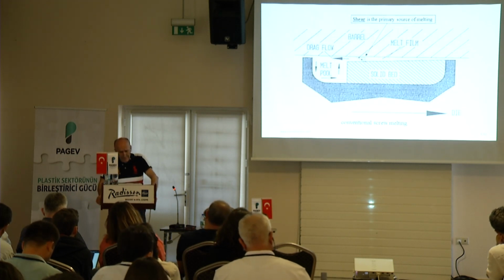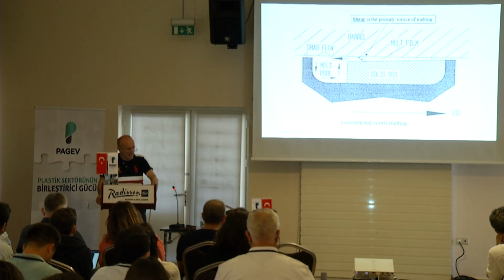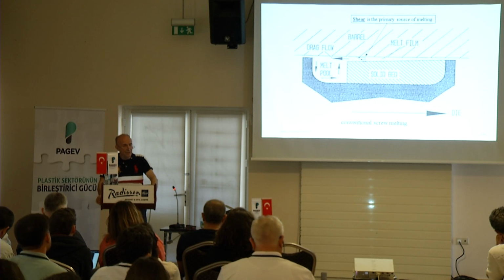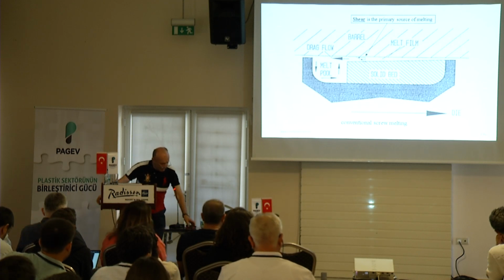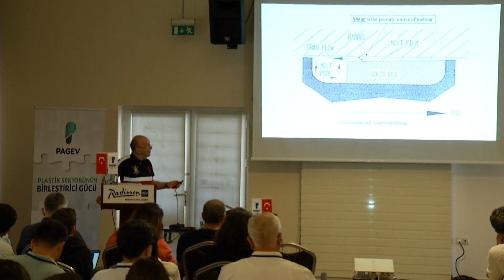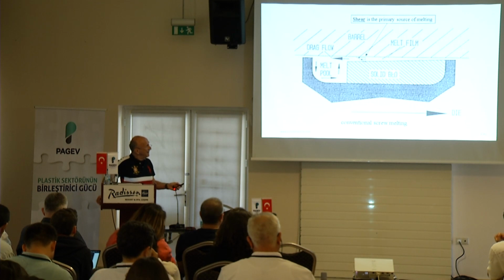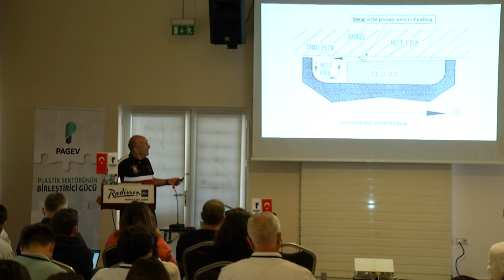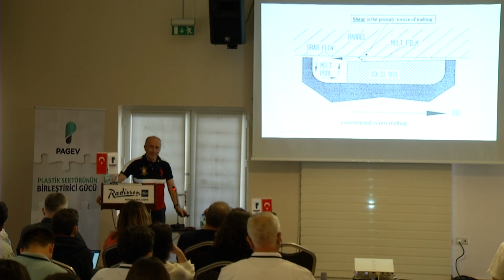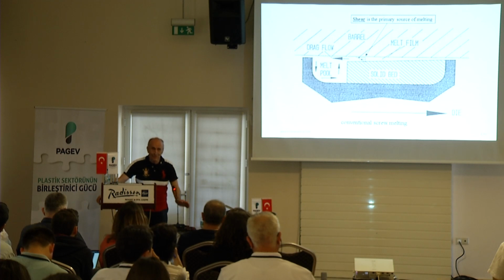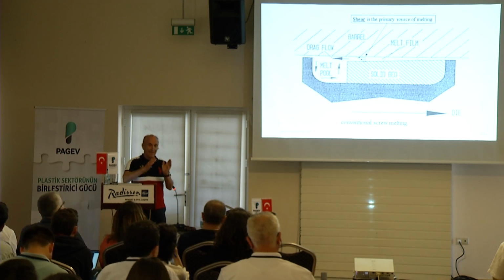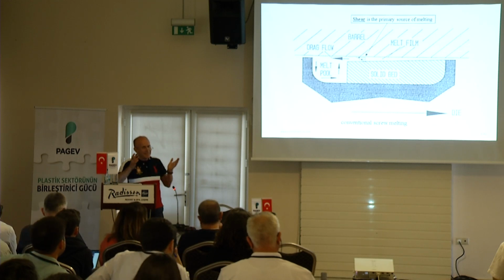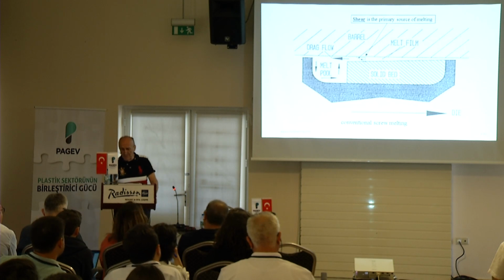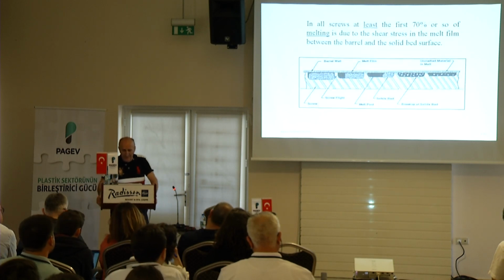Now, how was the barrier screw design developed? You see, we have this kind of melting mechanism from Bruce Maddock. You see that we separate the solid bed from the melt pool. Well, what if we actually put another flight right there? Where the solid bed ends, we put another flight, a barrier flight, to separate the solids from the melt pool. That's the basic principle. But this basic principle, of course, has generated a lot of designs.